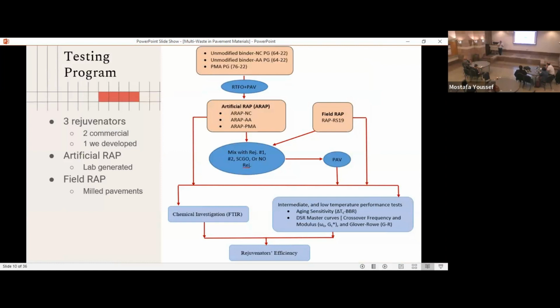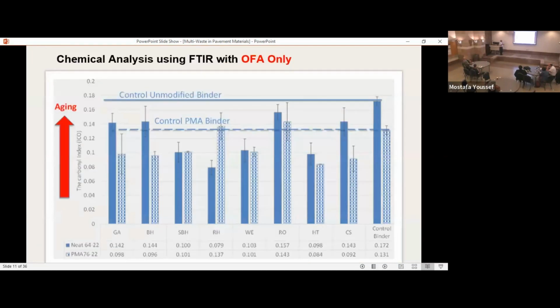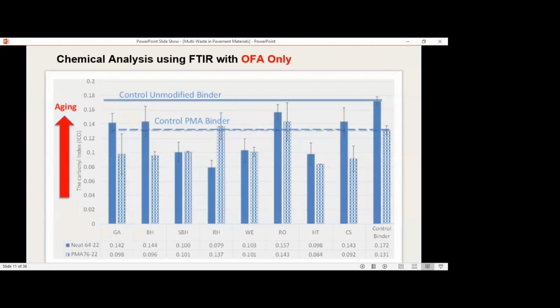We looked at this step-by-step approach. Again, the focus is the synergy, not whether these materials work or not. So we created this detailed experiment between these additives and the aged asphalt. We already established that it improves aging resistance. So if you look at the columns, this is an unmodified asphalt. This is the level of aging, measured by FTIR, the measurement of the formation of carbonyl compounds, which is directly related to the oxidation process. You can see that with all these different types of additives, we have a reduction in the aging.